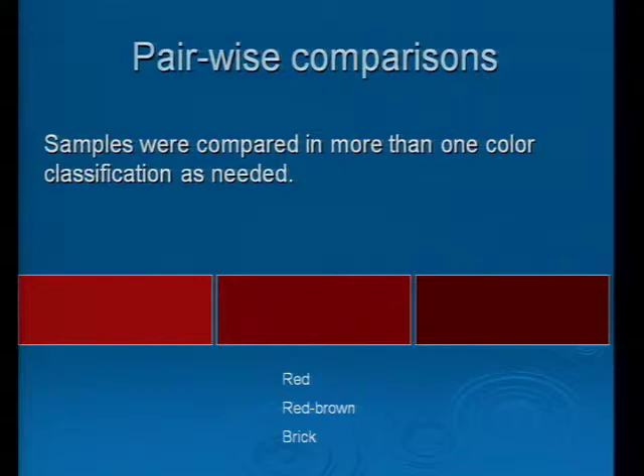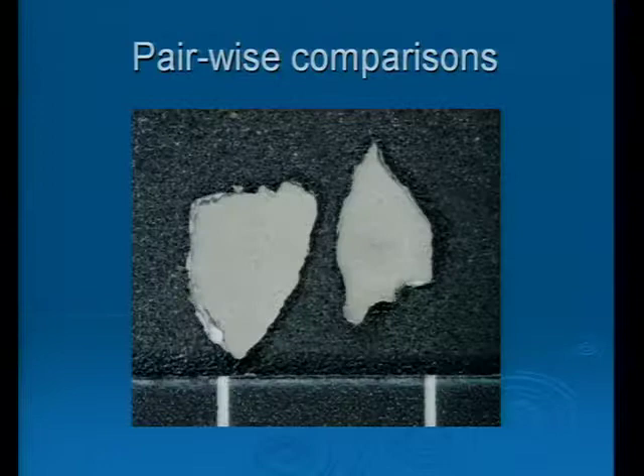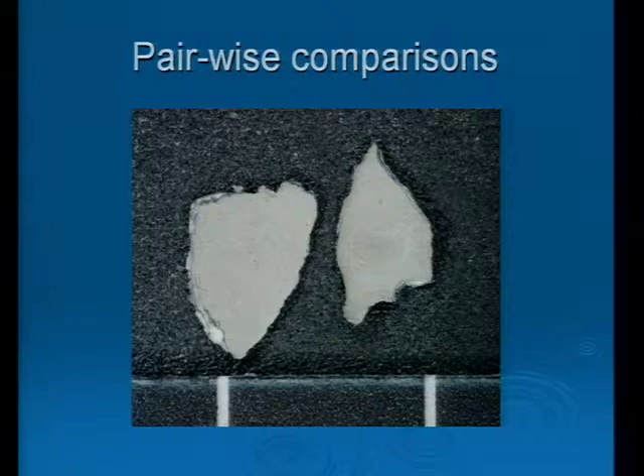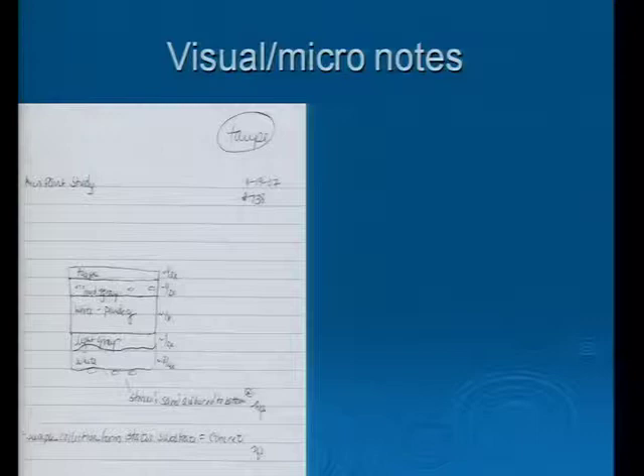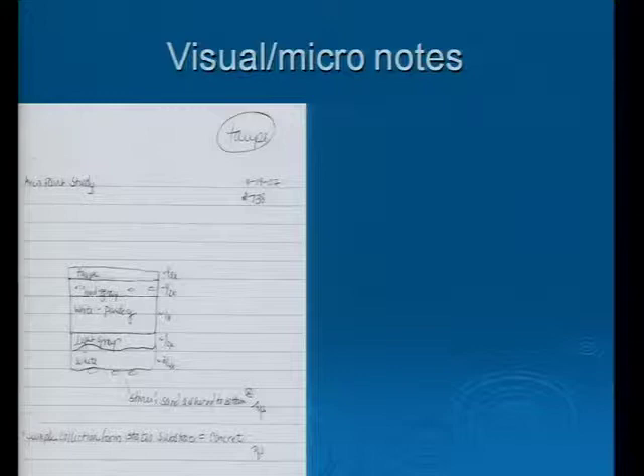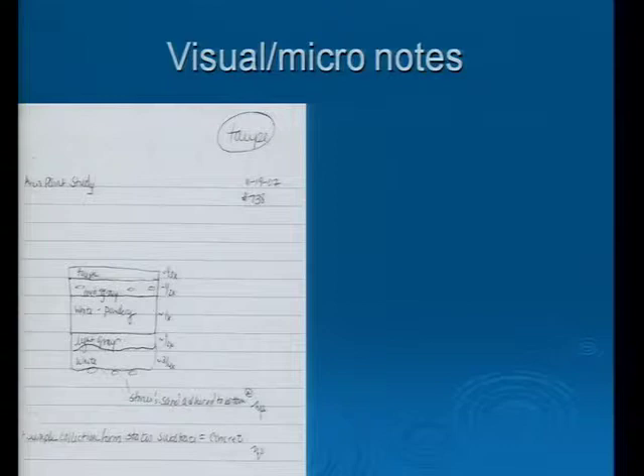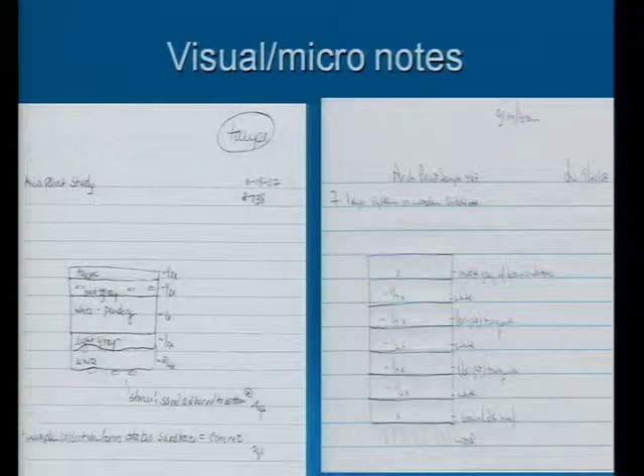Here is an example of two samples that we compared. You can probably tell that they both have more than one layer, but if you just looked at the top coat, those samples were indistinguishable. Looking at the underlying layers, the one on the left was characterized as having a taupe-colored top coat; the second layer had air voids and was classified as medium gray, then there was a thick white powdery layer — a five-layer paint system. That sample compared to the one on the right, where top coats were comparable, showed an underlying layer chemistry of white, turquoise, white, turquoise, white, and then brown — a seven-layer system, quite different from its pair.